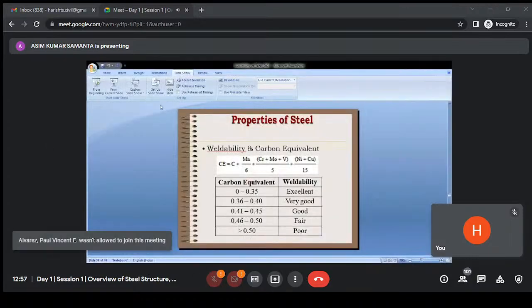Then corrosion. We are coming to that now. How to assess the corrosion? Sorry, weldability. Any steel member during fabrication will be joined either by bolting or by welding. We have to know that the steel should not be non-weldable. It has to be weldable, otherwise you cannot fabricate the structure. To know the weldability, there is one formula, called carbon equivalent. The formula is given here. If you go to IS 2062, you will find this formula, where carbon equivalent is assessed based on the steel chemical composition, and depending upon the carbon equivalent, weldability is defined.